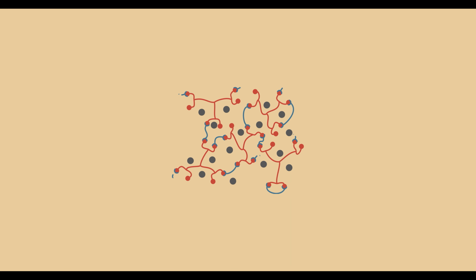Given the nearly infinite degrees of freedom of soft robots, it is not only useful to obtain information about their environment, but also about their own shape. And when working with self-healing robots, it is important that their embedded sensors are self-healing as well. To achieve this, the first step is developing conductive self-healing polymers, which was done through the addition of carbon black particles to the self-healing matrix.